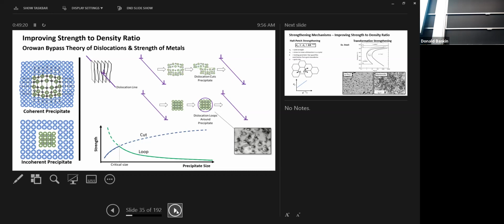When they're really small, like down over here, when a dislocation moves through the lattice and gets to that precipitate, in order to keep moving, what they have to do is actually cut through the precipitate. That takes a lot of energy. That's very effective at strengthening materials. When these little precipitates keep growing bigger and bigger, eventually it gets to the point where it's thermodynamically favorable for the dislocations to actually wrap around the precipitate.